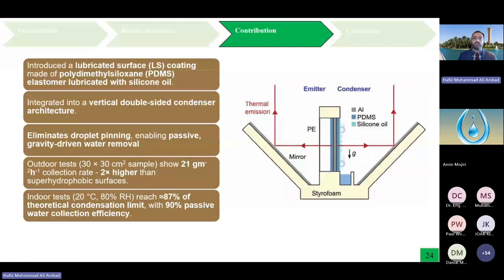And we were able to achieve 21 gram per square meter per hour water collection, and that can go for the case of super hydrophobic surfaces. If we compare the silicone oil with the super hydrophobic surface, this is almost double what has been reported in the literature. We also went for indoor tests. So the maximum condensation that was achieved was almost 80 to 90%.